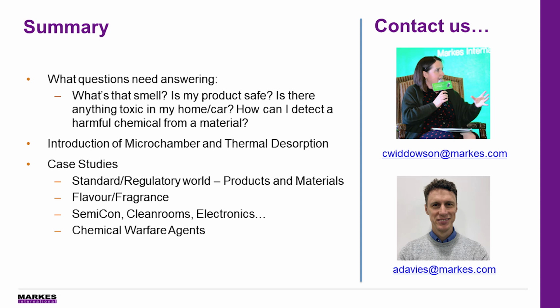However, the microchamber itself has small little fans on the top. So when you elevate that heat, we do have a fan that will draw the lab air to blow over the outside of the tube to try and reduce that temperature. But we do tend to recommend short sampling times when you're running the microchamber at very high temperatures. The other thing we can look at there is the strength of the adsorbent material inside the tube for the compounds that you're looking at. And if you have a specific application, please just drop us an email and we can give you some much more specific suggestions for that application.